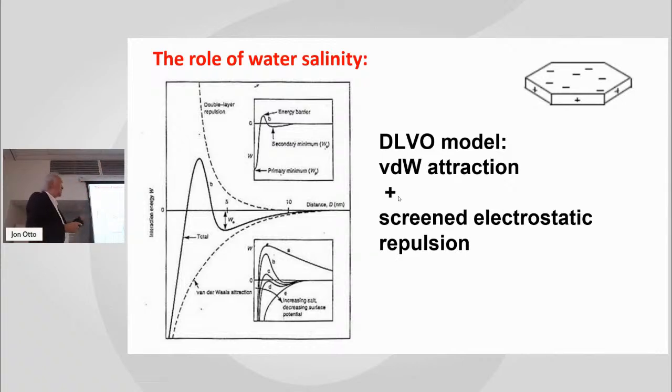So the more salt you add, the more screening you have. That allows you to get into a regime where this system can become attractive instead of repulsive. So the repulsion will decrease when you add salt. Eventually, it will become attractive. And this you can easily observe in many situations.